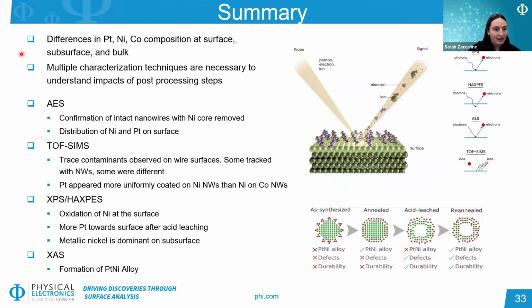So in summary, this is one of the main reasons why it's very beneficial to use these different techniques and compare them, because by looking at the different spot size and detection limits, we are able to quantify how our chemistry looks at the more outermost surface as well as the subsurface. And specifically in this data set today, the Auger technique also showed us that we did have the nanowires remain intact even after the acid leaching removed the majority of the nickel or the cobalt. We did see some of them breaking up, but overall they still remained intact.